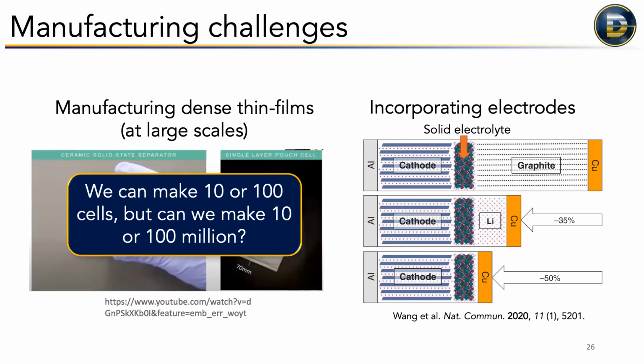One thing that helps is when we're using lithium metal, actually all of the lithium can in theory come from the cathode rather than the anode, which means that you actually don't need to handle lithium metal when you manufacture the battery. You can make the cell without an anode and then just plate out a lithium metal anode on the current collector. So this basically removes a third of the manufacturing cost straight away because you don't have to manufacture an anode. Plus you don't have to work with lithium metal, which is very reactive, not stable in air, all kinds of problems.